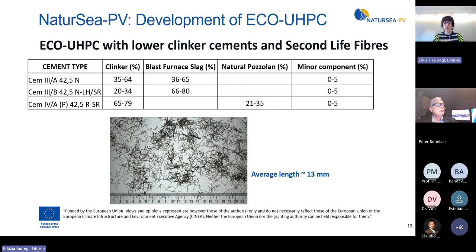Usually, ultra high performance concrete is prepared with OPCs, especially CEM I, using large amounts of CEM I. In this occasion, we want to use, as I said before, lower clinker cements. These cements have been provided by Holcim. Also, we've used superplasticizers developed by Fosroc and Bauchemie to obtain the mixes. And for recycling, we have decided to substitute steel fibers with second life fibers from Flexo Fibers.